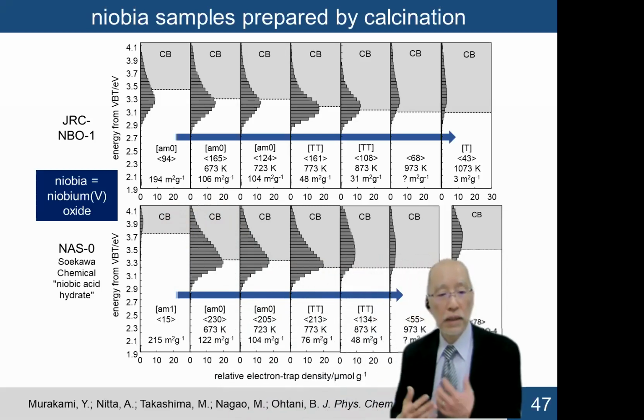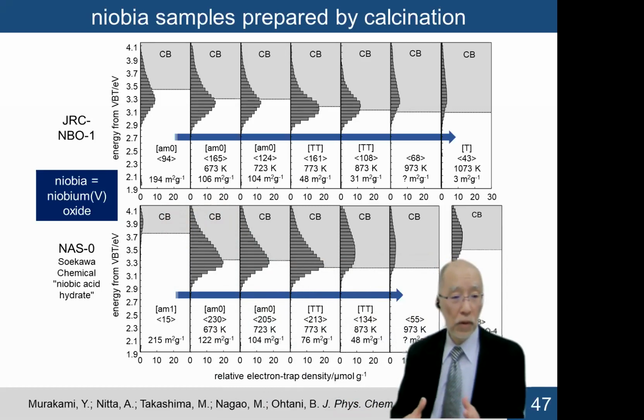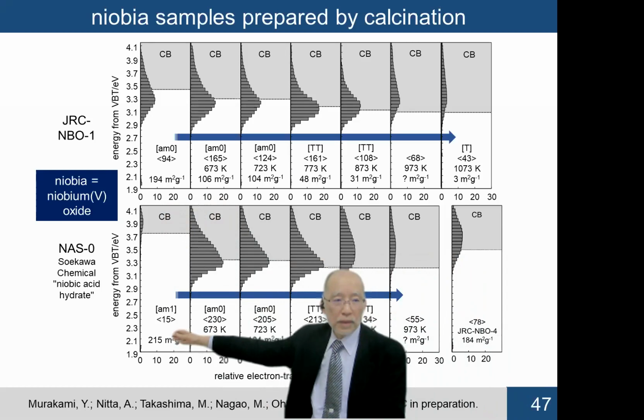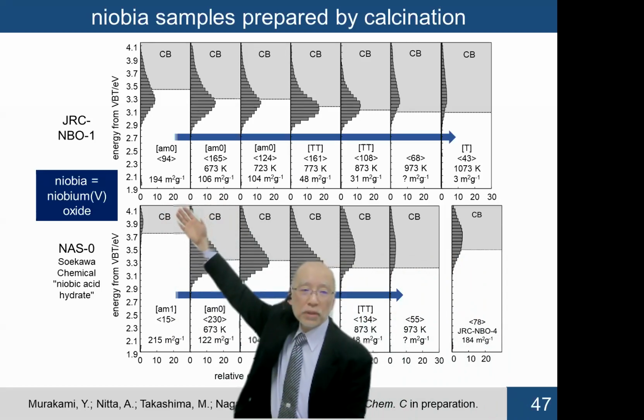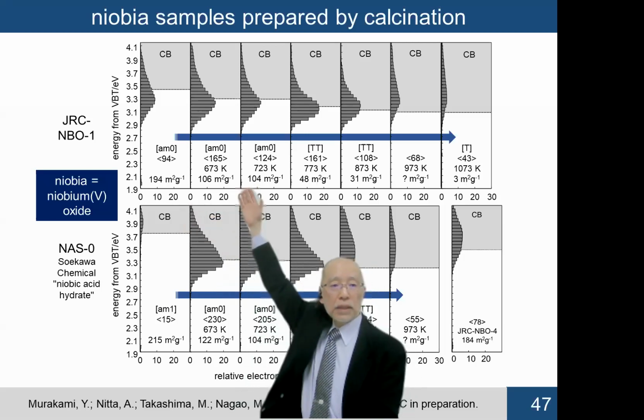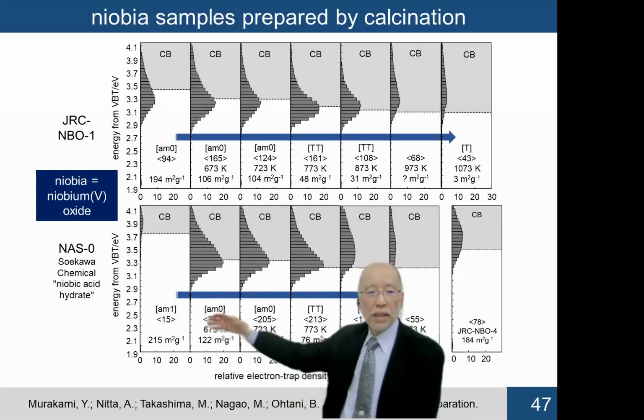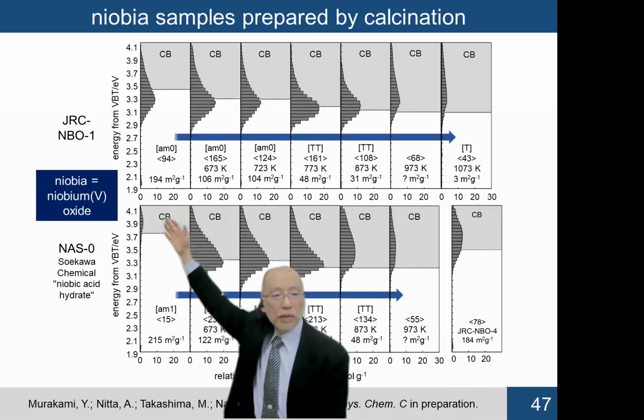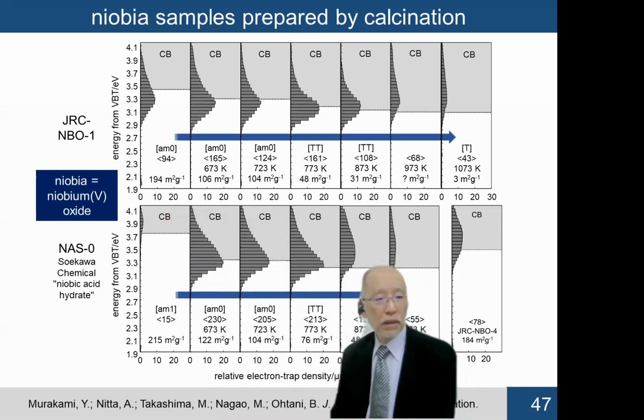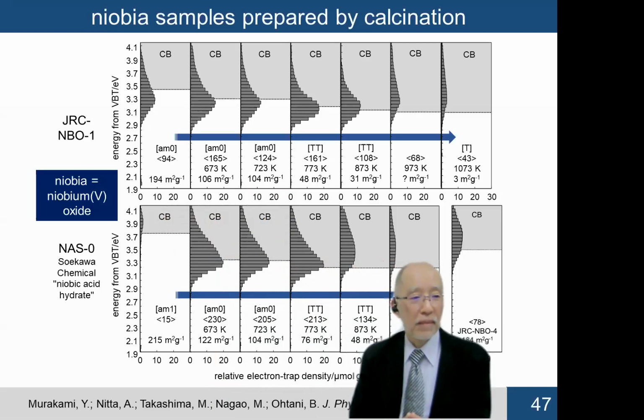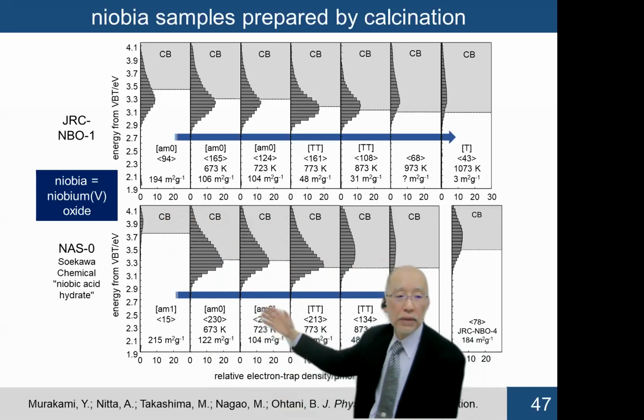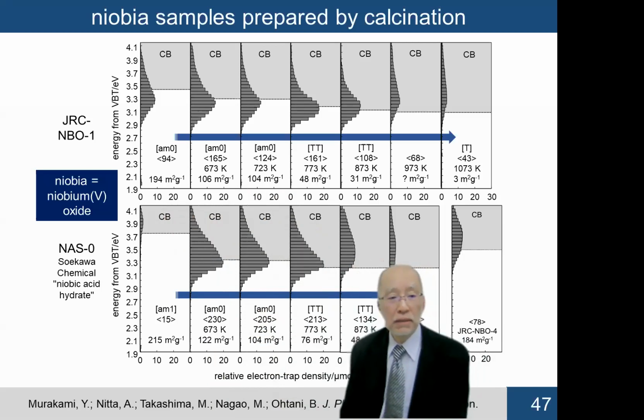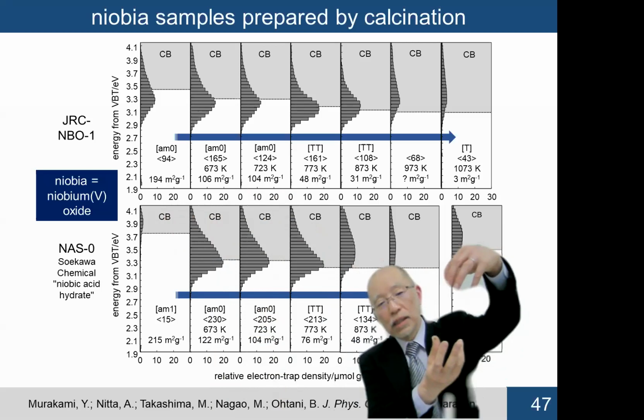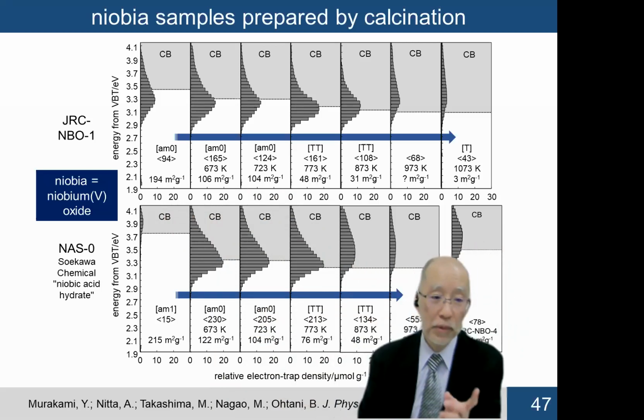The left top and left bottom are different starting materials of niobium, Nb2O5. Probably this is niobic acid, and this is probably amorphous niobium oxide. By heating at this temperature, the pattern changes. You can see the completely different ERDT patterns of the left two samples, the starting materials, which means they are different. But by heating at this temperature, the pattern becomes a bit similar. So the starting materials are different, but heating gives almost the same material, probably niobic acid, but still not a completely crystalline material.